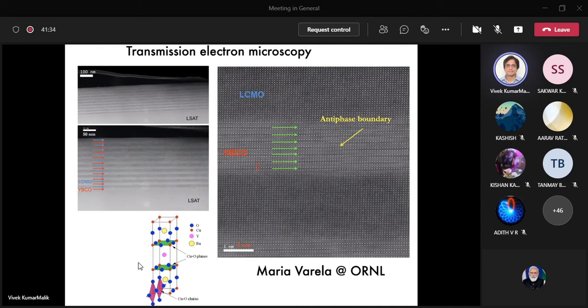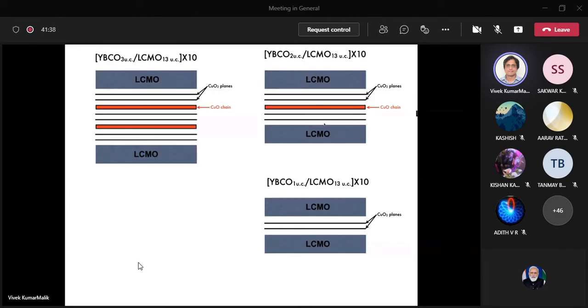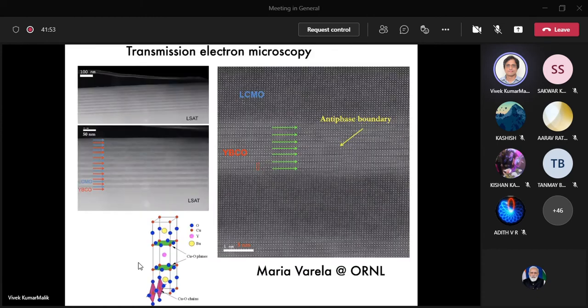Okay, so yeah, this is the transmission electron microscopy picture. So what we can do is grow layers of different thicknesses, YBCO, LCMO, like 13 unit cell. But what we also observed is that at the boundary we do not have the chains at the interfaces of this YBCO LCMO. It grows in between.